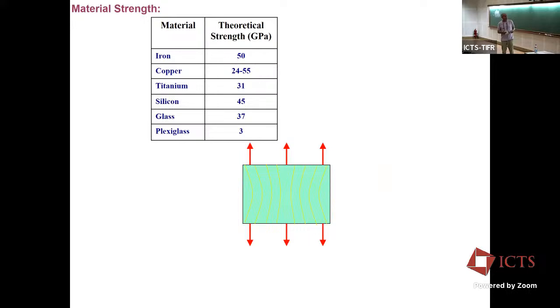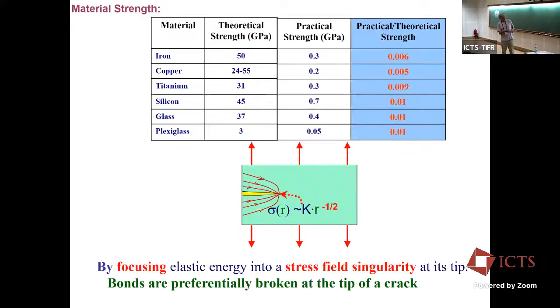Okay, so just for fun, for anybody that doesn't believe me, these are the theoretical strengths for a bunch of different materials. These are the practical strengths, and this is the ratio, orders of magnitude. And this is without actually making a macroscopic size crack. These are from the microscopic size cracks that always exist, the microscopic defects. And you can already see that the practical strength is much, much less than the theoretical strength. It's funny though, you can approach the theoretical strength of a material if you get rid of the cracks.